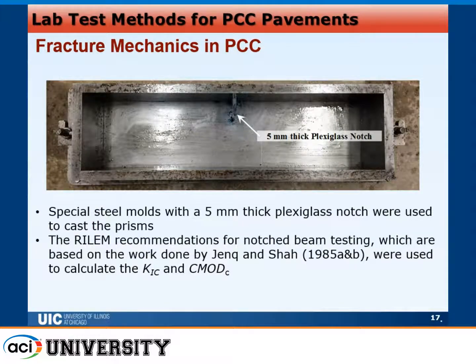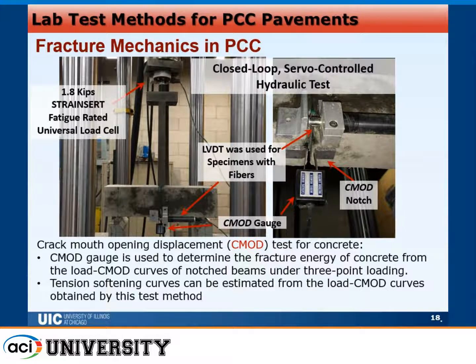The notch was initiated using steel molds with a plexiglass notch, 5 millimeters thick. And this is the machine that I was talking about. This is the CMOD clip gauge attached at the bottom of the beam, and an LVDT at the same level in the transverse direction was also attached, only for the case when we have fibers. For fibrous concrete, because it takes much more crack mouth opening displacement, the CMOD gauge can go out of range, so we attached this LVDT as a backup. At the point where the CMOD goes out of range, the LVDT will pick up and we'll continue. We have extended data after the range of the CMOD.